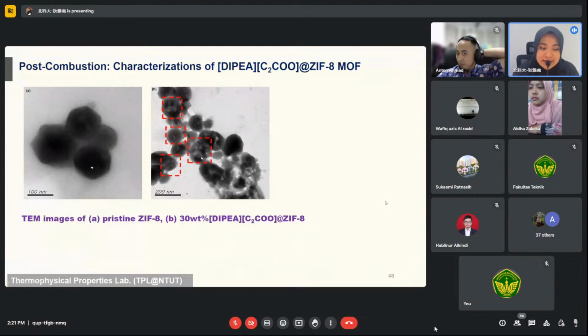So this is just confirmation of the form and the surface layer of our compound, whether our material becomes a totally successful composite or not. If we compare here, it's successful, the ionic liquid totally goes inside the pore of the metal organic framework. So we can see the proof.